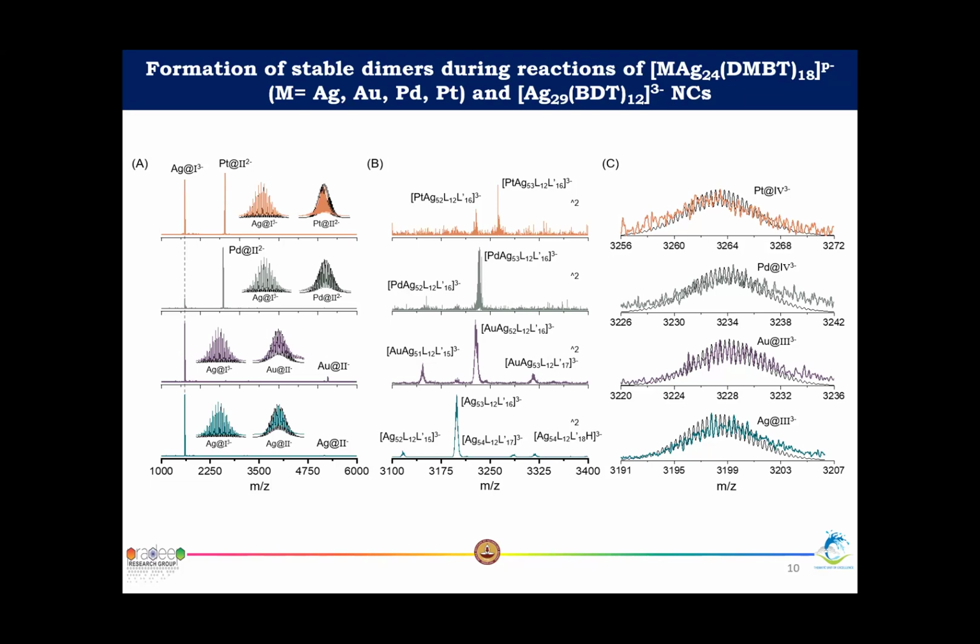There are many other thoughts that you can have, many other techniques. For example, Amog mentioned X-ray. There is a technique called small angle X-ray scattering. This, of course, looks at the size and shape of particles, very similar to dynamic light scattering, but far more resolved. A similar thing is possible with neutron scattering: a smaller cluster becoming larger, and their transient changes.